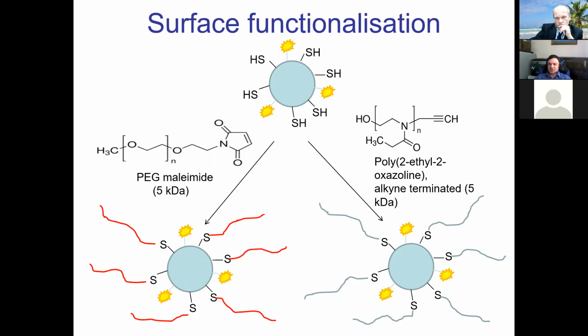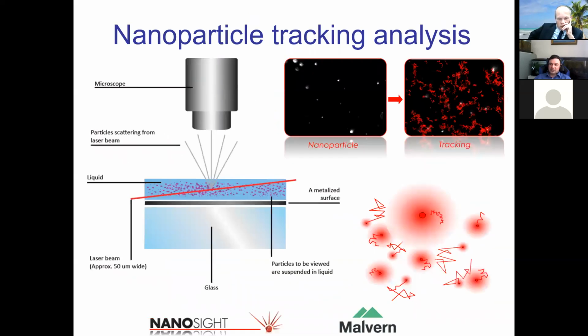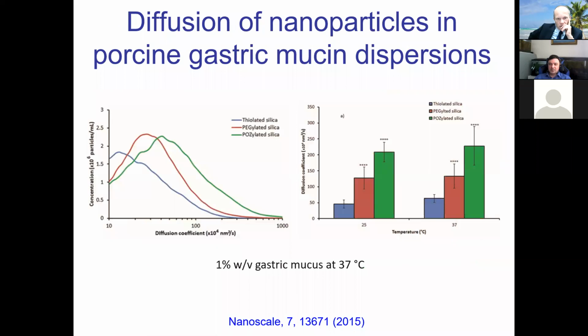We designed a series of particles which were either modified with PEG, so they were PEGylated, or also we designed systems which were POXylated, so they were functionalized with polyoxazolines. And we have used nanoparticle tracking analysis to follow the diffusion of these particles in mucus dispersions and demonstrated that the particles that were modified with PEG and with polyoxazoline, 2-ethyloxazoline at that time, were more diffusive than the sticky thiolated silica. So our group was the first to demonstrate that polyoxazolines could improve diffusiveness in the mucus.